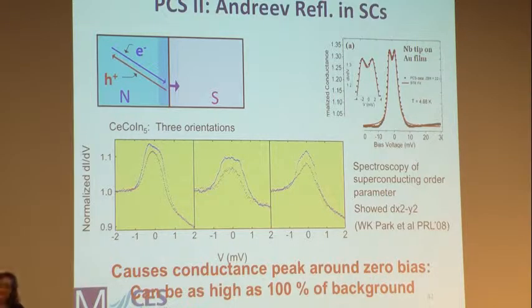And there's a very well-cited paper by Blonder, Tinkham, and Klapwijk, where they actually looked at what would happen if you went from the tunneling to the clean regime. And they were able to define this, just a simple, blind application of the Bogoliubov equations. If you have electrons injected into a superconducting film, and this is data taken by my undergraduates, it's beautifully modeled. It gives you the gap. It gives you the gap symmetry. It gives you a whole bunch of information about the superconducting properties.